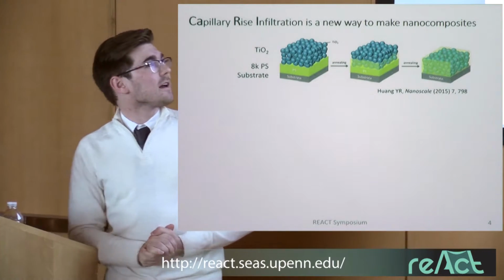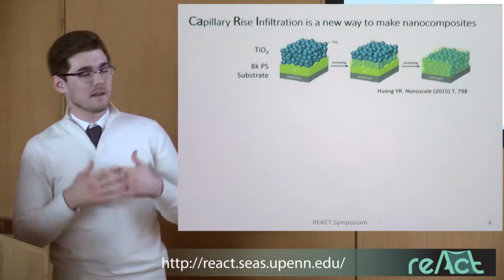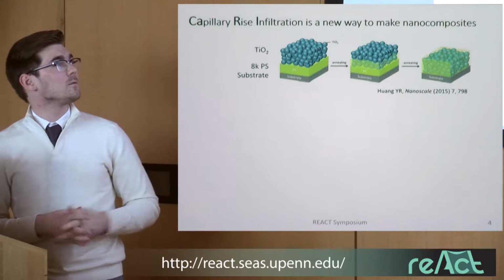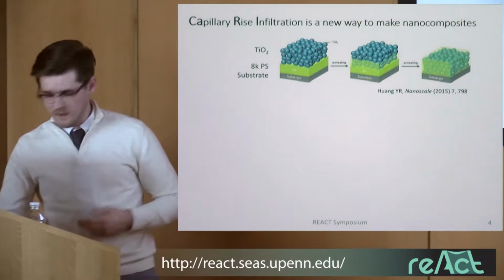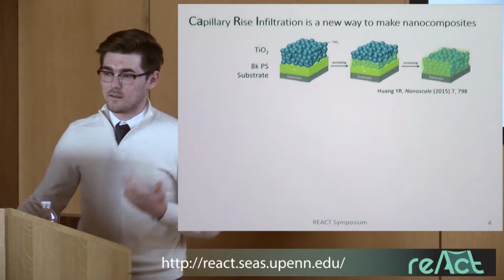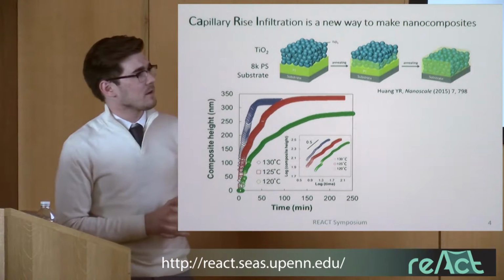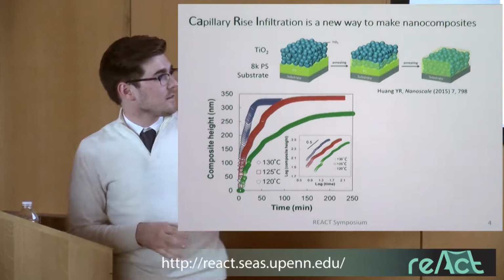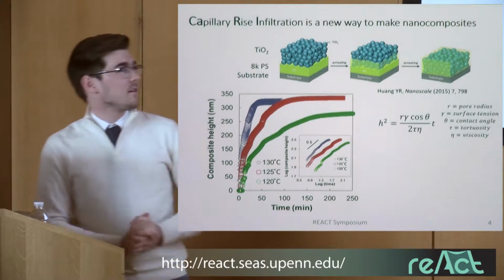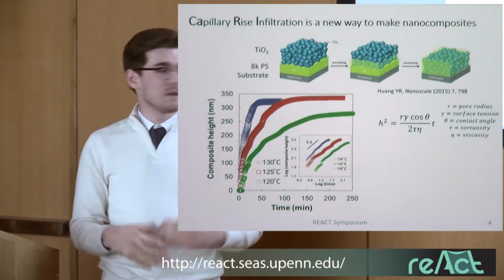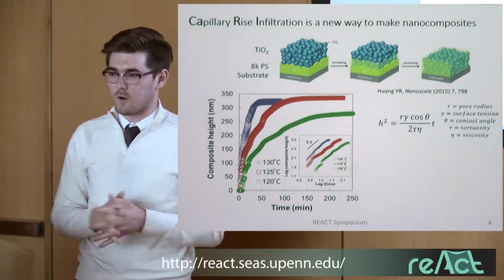So the previous work that has been done with this is to take polymer and nanoparticles, in this case a short chain polymer, and to perform this capillary rise infiltration process that Neha talked about. And we have demonstrated in the past that we can generate very high filler fractions of nanoparticles. If you look at the dynamics of this process, the inset here shows that it follows a very particular scaling, which is consistent with this equation called the Lucas-Washburn equation, which governs capillary infiltration into different media, including, say, water and sponges.